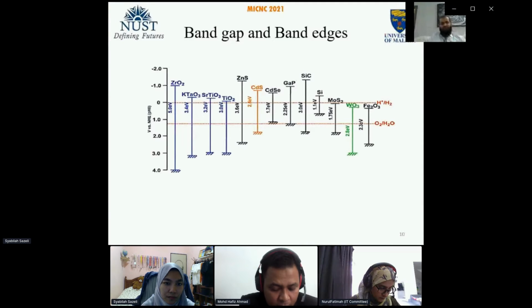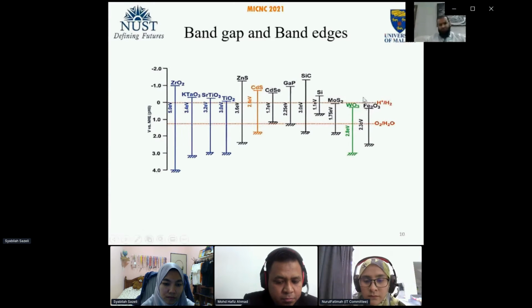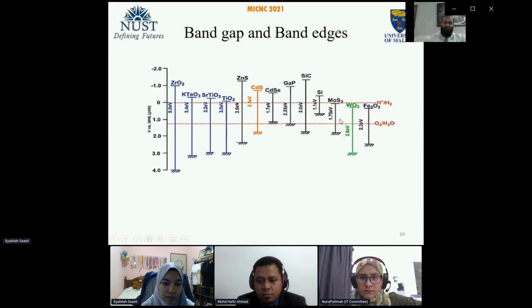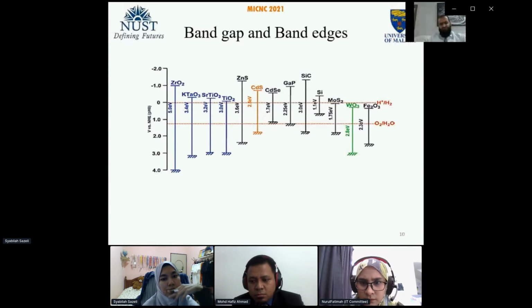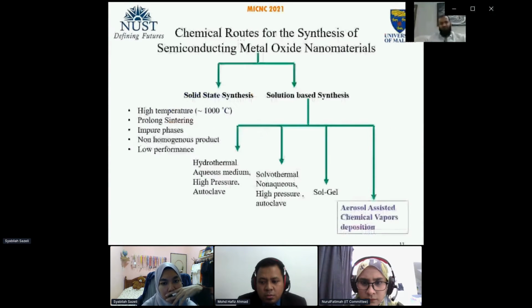Apart from the band gap, the band edge is also important, and it confirms whether the material is going to be used as a cathode. If its band edge is close to the reduction potential of water, it will act as a cathode. And if its band edge is close to the oxidation of water, it will act as an anodic material. Most of the materials we have synthesized are photoanodic materials. Similarly, in the present study, we have also prepared a photoanodic material.